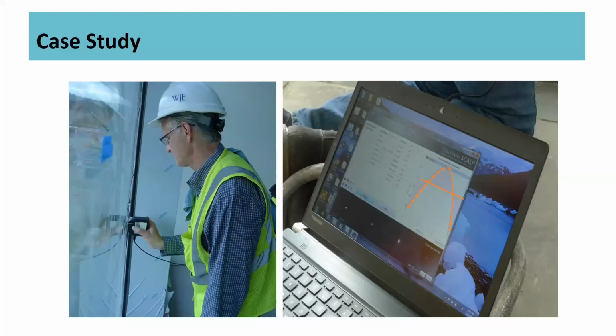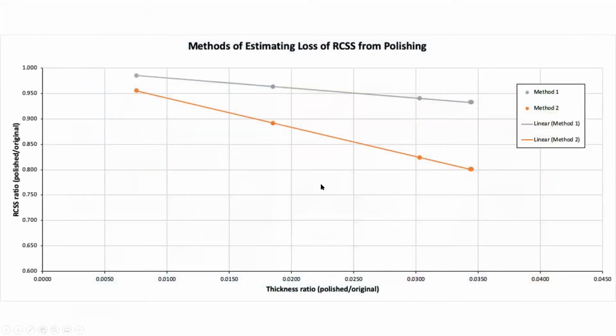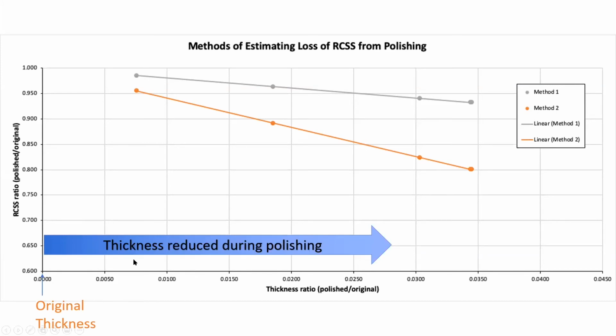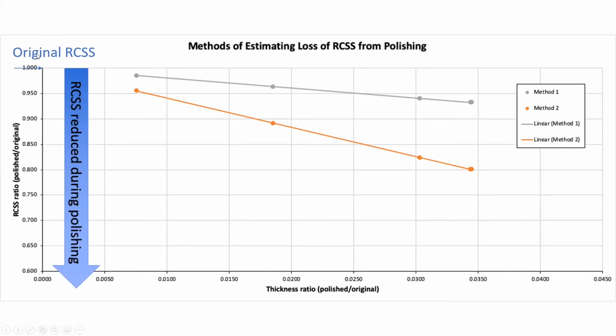And with that information, we were brainstorming, from before we polished, what the RCSS could end up being. Okay, so before I get into that, I want to orient you to my axes. On the x-axis, I'm showing a ratio of my thickness being reduced. So think of it as, this was our original thickness, and as we continue to reduce the thickness through polishing, we're moving in this direction. So this is the most that we remove. Now remember, this is a ratio, so these aren't actual dimensions. On the y-axis is where we started, the original RCSS, and as we do polishing, it would reduce going down, okay?